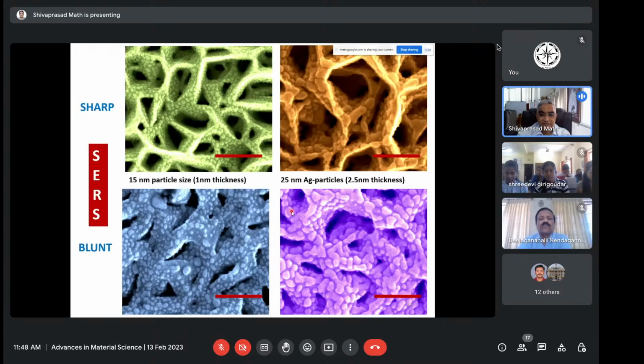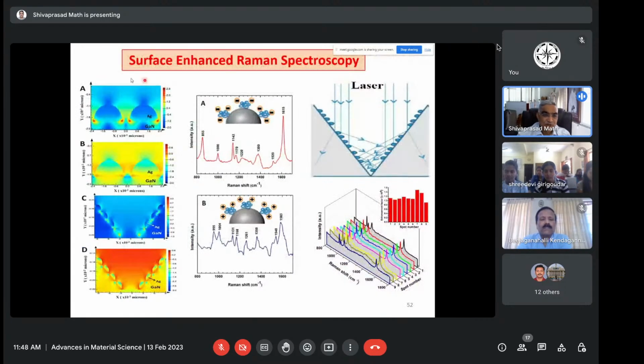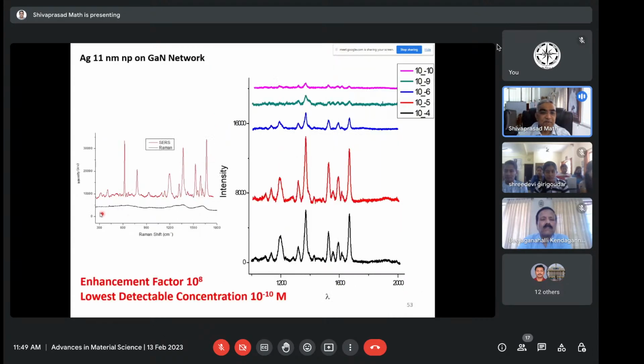By putting the silver particles on these materials, we tried to see how it happens, and also did some simulations to see where the hotspots are and how the energy is distributed. Then we found it is possible to see that. When we do the experiment, this is the normal Raman signal we can get from a material. Once I put silver nanoparticles, look at the beautiful signature it has. The fingerprinting becomes so much easier with these nanomaterials. With this, we could detect up to 10 to the power of minus 10 molar, the lowest detectable concentration. So this becomes a very important material for detecting early diseases. This was just because of the coupling of the surface plasmons in the nanoparticles.